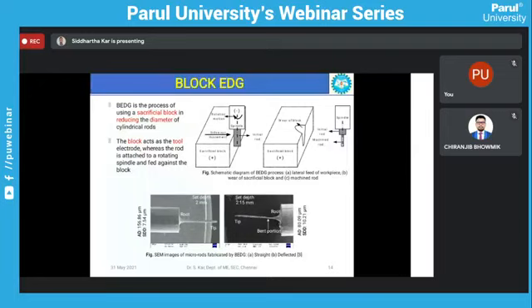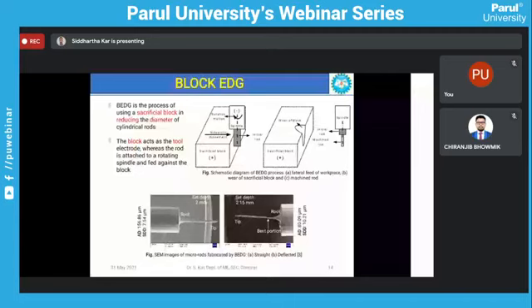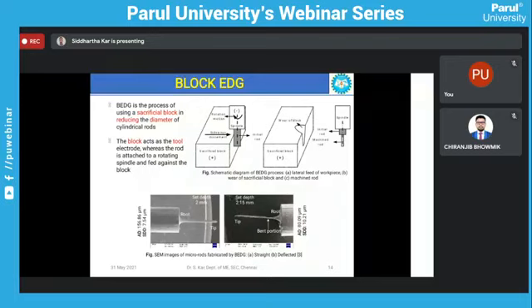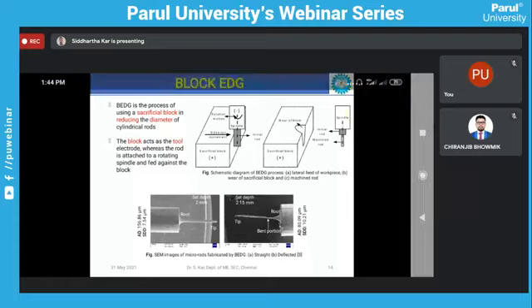The set depth has been increased from 2 mm to 2.15 mm. We see the root portion has been bent and the tip is also deformed. This suggests that the tool made some mechanical contact. Although EDM is a non-contact process, there is very little gap between the workpiece and the tool, and moreover dielectric is also supplied, so chances of mechanical contact are also there. So we have to choose the set depth very accurately in order to fabricate micro rods with higher efficiency and without any failure.